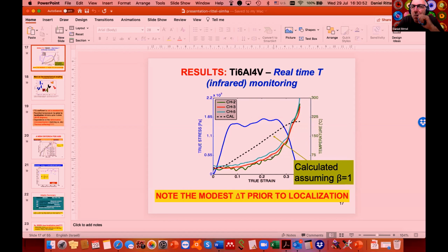Yeah, I understand. But in the beginning of your discussion, you said it's a competition between thermal softening and strain rate hardening. Yes. That depends very much on the material. You see, in order to generate heat, you need sigma and you need epsilon. We agree. Usually materials have sigma, they don't have epsilon, or they have epsilon and they don't have sigma. At the end of the day, it's an integral. So you have to make your choice. What brings you the maximum temperature or most of the temperature?